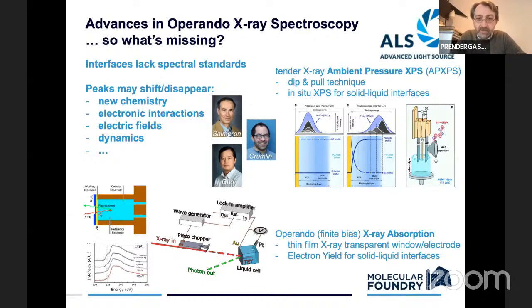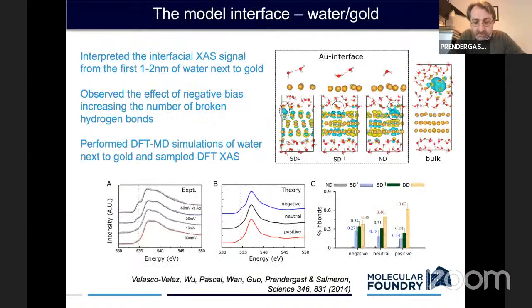So with that in mind, some years ago now, back in 2014, we had done some work looking at kind of a fruit fly example of a model interface, right? So water next to gold. There's really nothing going on there from an electrochemical point of view. It's a very simple system. And what you observe as you change the bias is a reorientation of the water molecules at the interface in this packed, densified layer. Now, what we were able to do was to translate those observations from molecular dynamic simulations, which would have been known in the literature, into X-ray spectral signatures. And it was at this point that we began to realize that this technique was really sensitive to this very first 1, 2, maybe 3 molecular layers next to the metal surface.